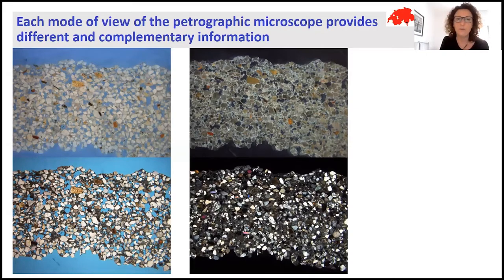I would like to say that with the different light, it's possible to have complementary information about a mortar in a thin section. For example, in the first image, in the bottom left, you will see the image of a mortar with reflected light, which is used mainly by cement chemists, but also for the study of the polished section, for example to observe the stratigraphy of a mural painting. And the same reflected light, but in the second image, with the dark field, is important to enhance the contrast of the image.